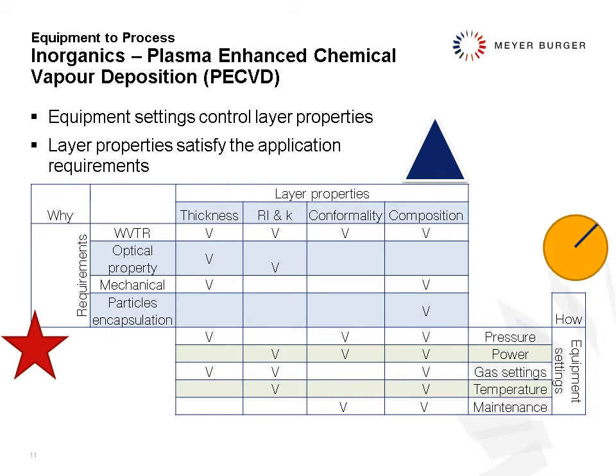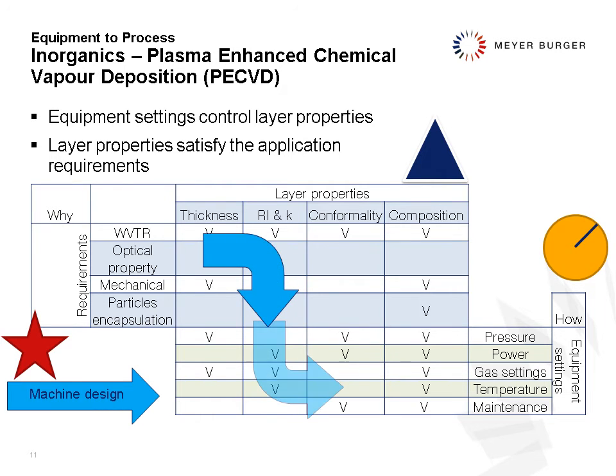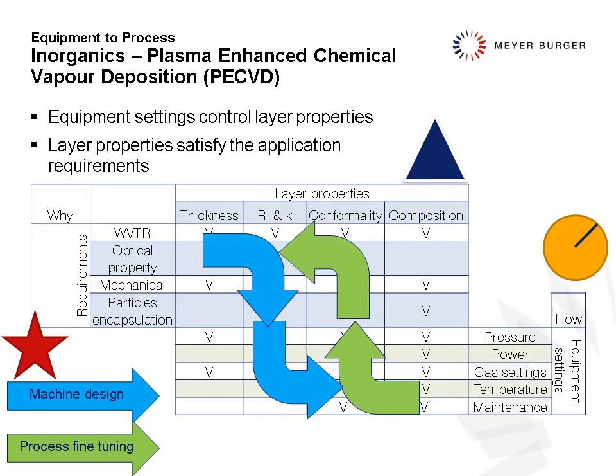We can go again through this table for the case of inorganics, and particularly for plasma-enhanced chemical vapor deposition of silicon nitride. Again, we have some knobs, which are pressure, power, gas settings, temperature and maintenance. Then we can influence layer properties of thickness, refractive index, conformality, and composition, and this will turn out to fit the requirements from the customer. Again, we will sit at the table with the customer, discuss the requirements, and therefore find out which machine is needed. And in the end, we will also go through a process fine-tuning to see if it all works out.